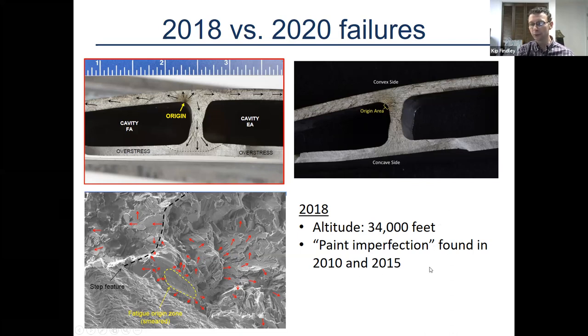What's a little bit concerning about this one is that in this case, there was a paint imperfection that was found through thermal acoustic imaging, or that's what they classified it as. So they saw an imperfection and they thought, oh, that's just paint. And they saw it both in 2010 and 2015. So they had a chance to take this engine out of service, but they didn't, because this non-destructive evaluation method wasn't perfect. They classified it incorrectly, and then ultimately this blade failed, right? So these are really important things to think about. The inspection and the maintenance of these blades is really critical.